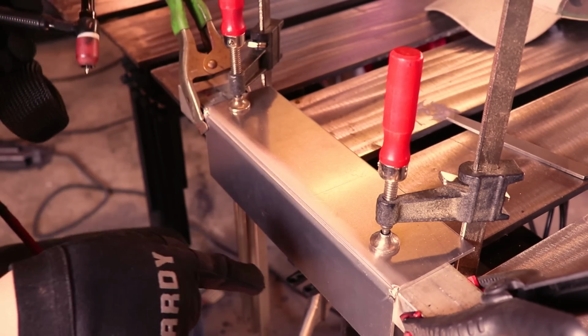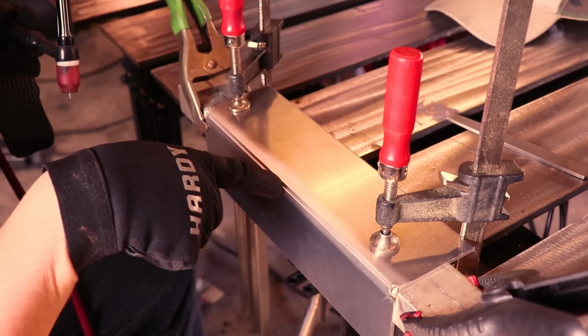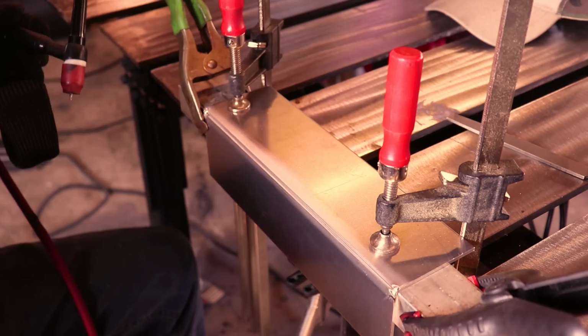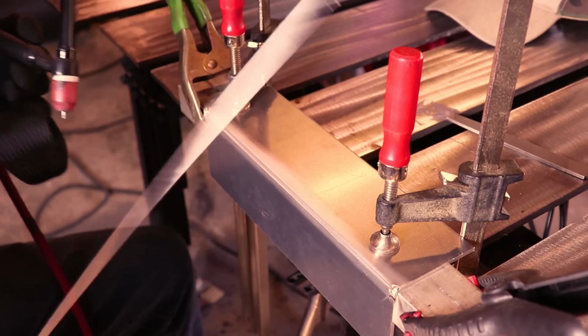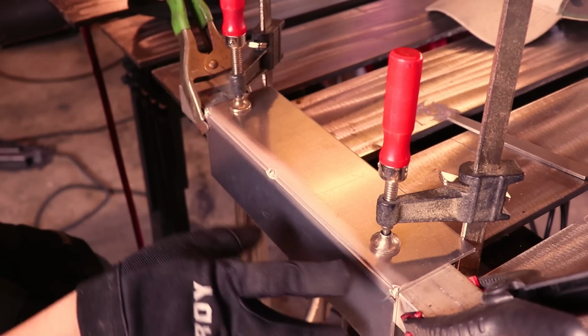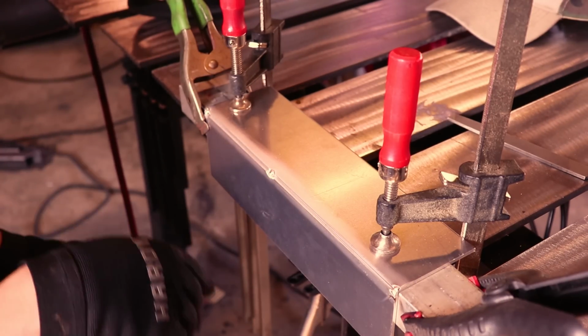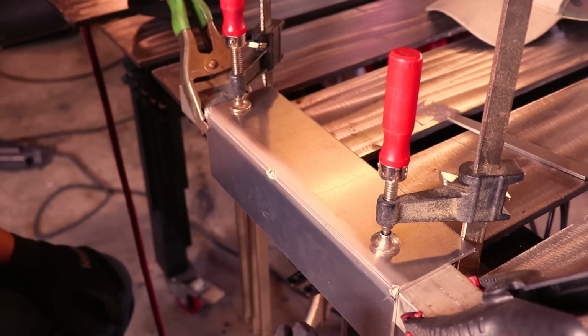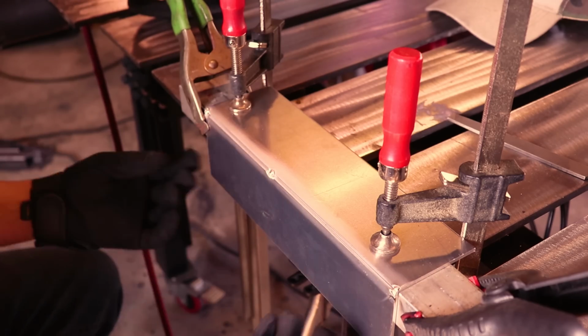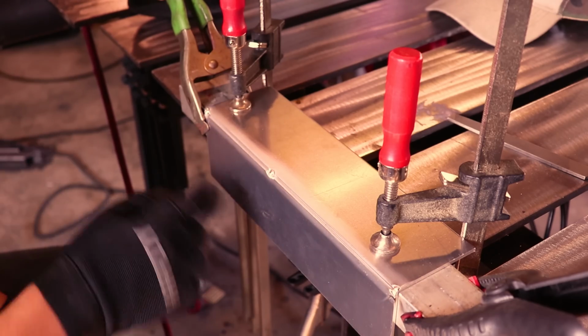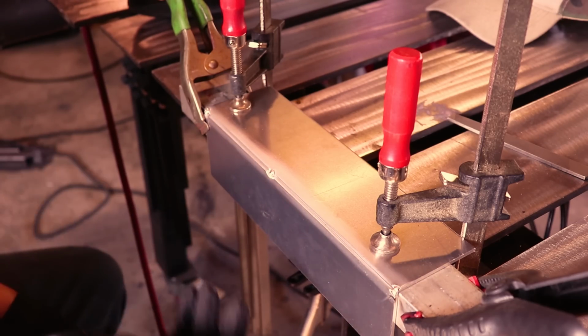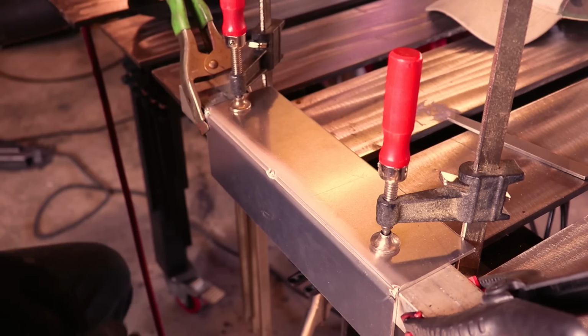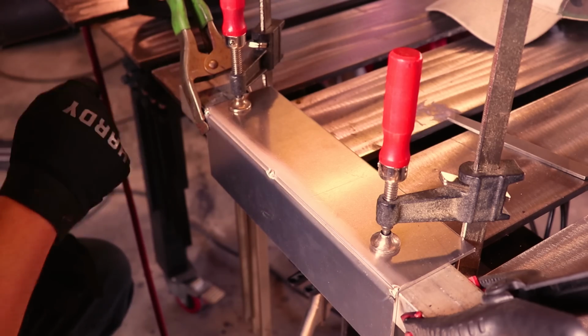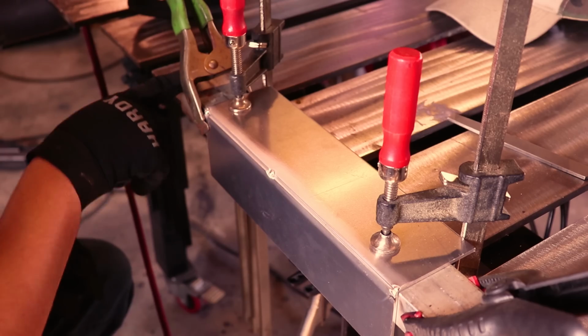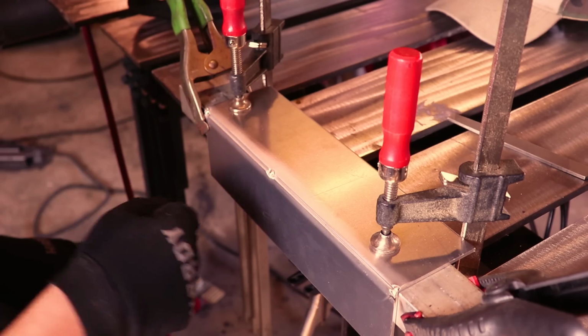On something this long, you really need to put another tack here in the center, especially on 1/8 inch. Now if you don't want any burn through, a good idea is to keep a bar like this behind it when you weld it. You clamp it down on both sides, and that'll keep it at a perfect 90. So if you have C-channel or something like that, even if it's a thick thing of aluminum behind it, it's not going to weld itself to it if it's something thin.